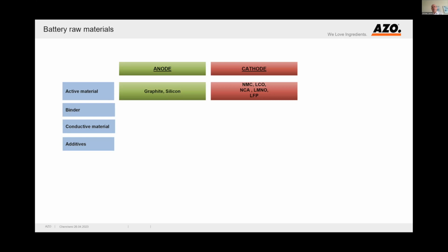The active materials for the anode are mainly graphite, also silicon, could be a share of 5 to 10% of silicon. For the cathode, we have many different chemistries like NMC, LCO, LFP, and so on. And also different grades of these chemistries. For NMC, for example, could be 622, 811, and so on. For the binders, on the anode side, we usually use CMC as a binder. For the cathode, the typical binder is PVDF.